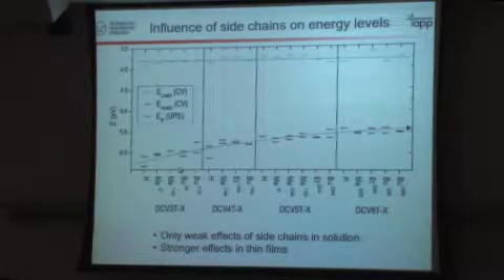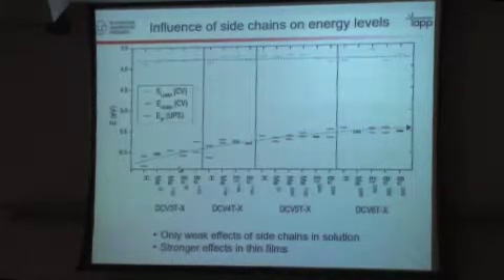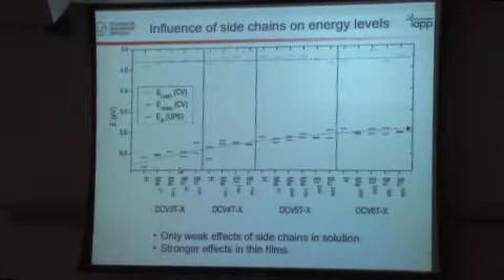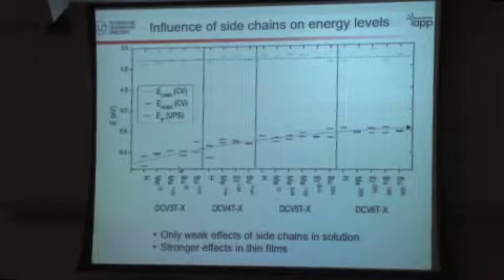However, if you look in more detail now at how this energy shifts for the different number of thiophene units, but also for the side groups, and you compare measurements in solution and in the solid state, the red data, you see that the solution measurements scatter only little as a function of side group. They basically change by the backbone length, but the solid state results in red, you see they make significant fluctuations with the side groups because you change the solid state morphology. So it is very complicated and very difficult to really control the energy levels.